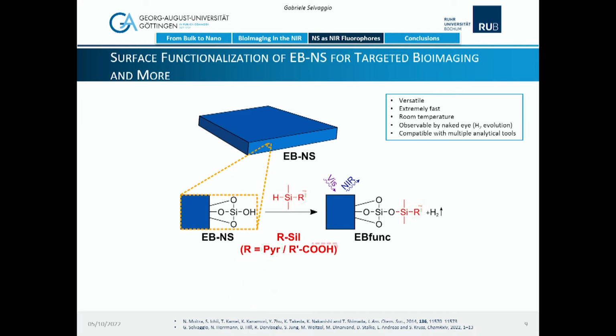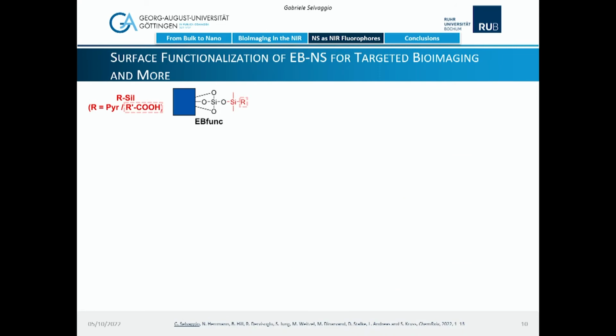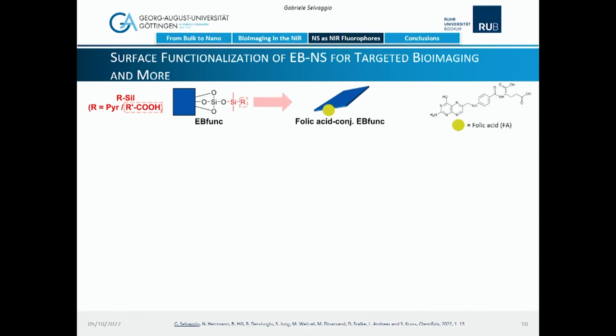And in the last part, we repeated the reaction with a different hydrosilane, with a different R group, with an alkyl chain ending with a carboxy group. And this allowed a proof of principle bioapplication of targeted bioimaging. I will jump directly to this. What was done here, so you imagine you have nanosheets of Egyptian blue with carboxyl groups now covalently bonded on the surface. And what we did was to conjugate on these nanosheets folic acid, which is vitamin B9.